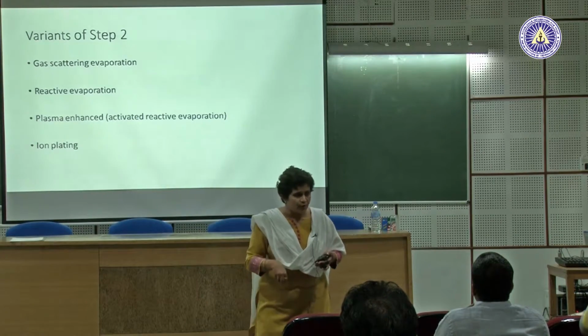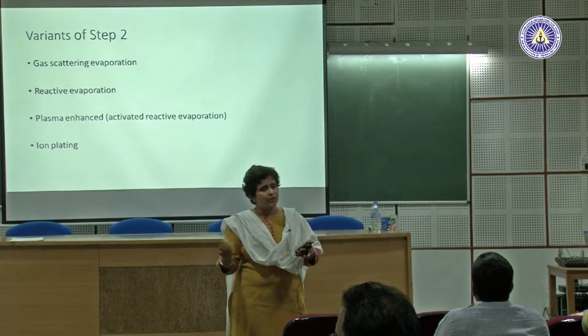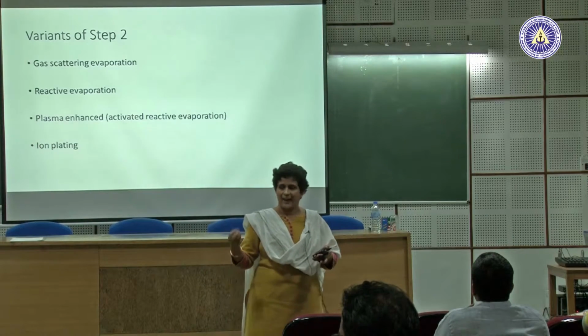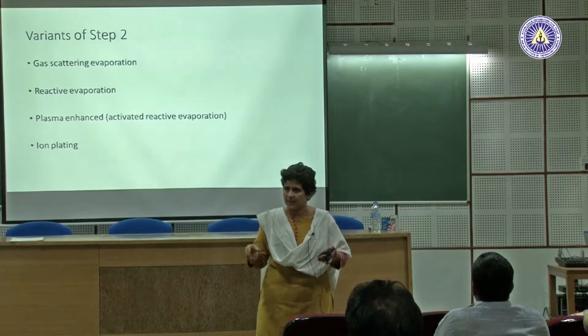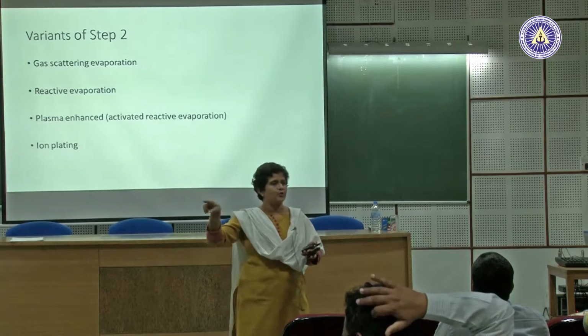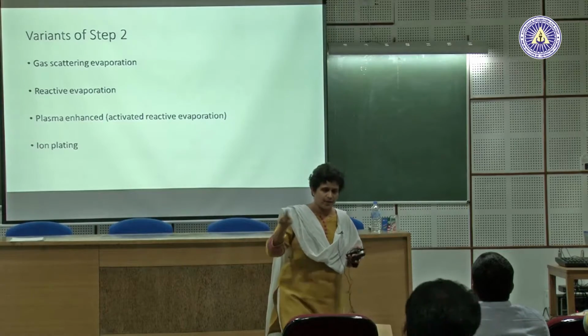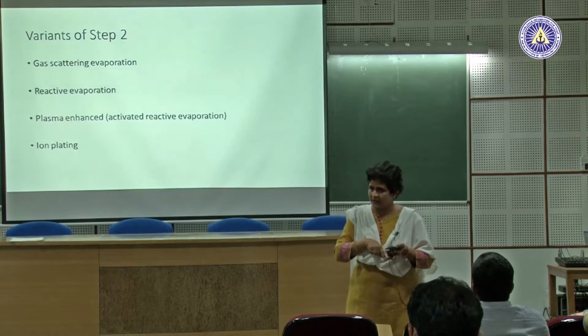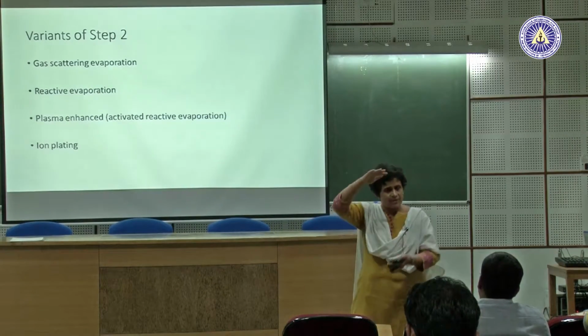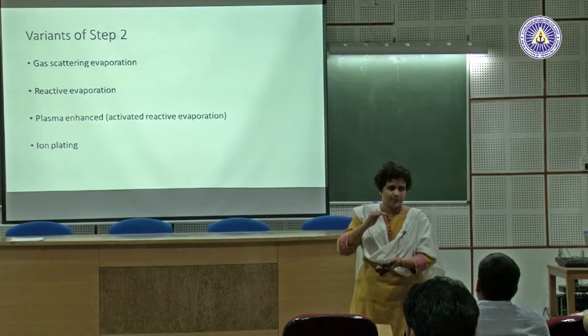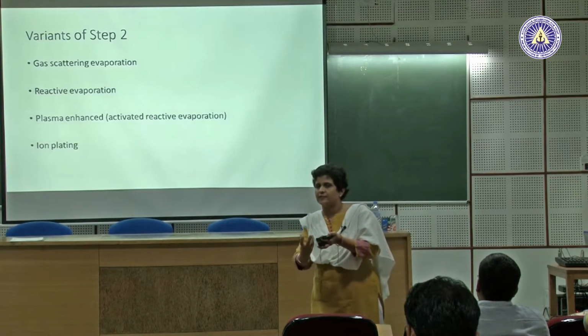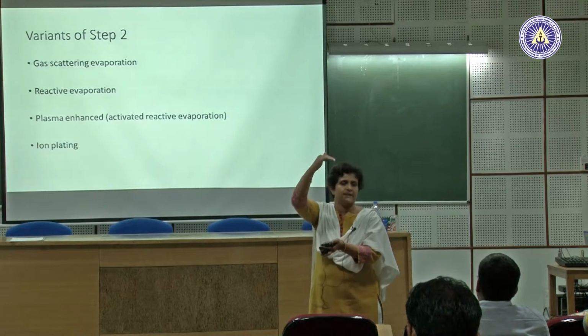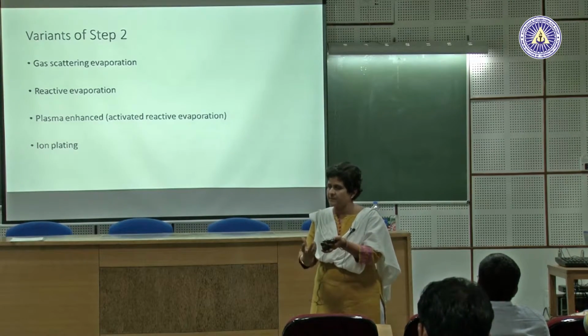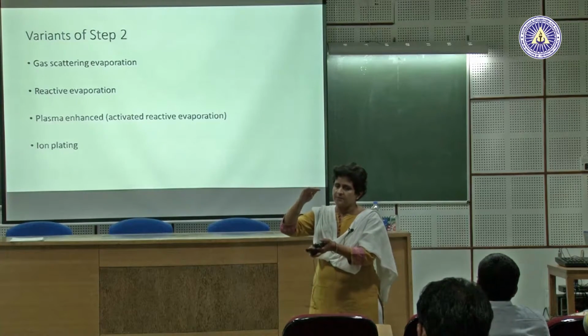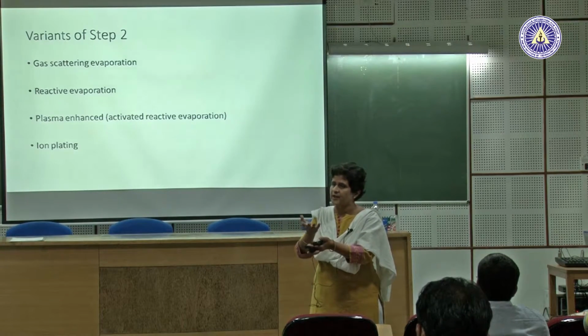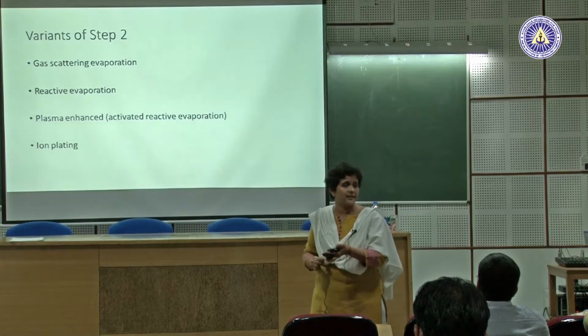So, what is the way out of it? If you make nitrogen into plasma form, what have you done? You have taken N2, you have broken it already in the plasma, it has become now nascent nitrogen atom. Now, this nitrogen atom is very likely to bind with silicon, right, and that is why with the evaporation system you create a plasma. You create a nitrogen plasma, silicon gets evaporated, it goes through that nitrogen plasma and then gets deposited. So, silicon vapors are getting created, it goes through the nitrogen plasma which has nitrogen atoms, it reacts with nitrogen atoms, and on the substrate you are depositing silicon nitride.